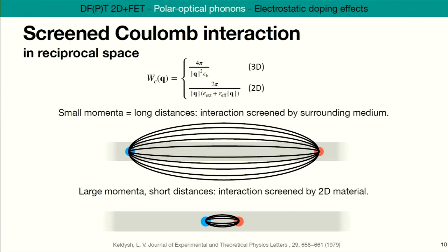So let's look at how it works. First, at small momenta. Small momenta correspond to long distances in real space. This corresponds to this term here being zero, or negligible at least, in front of the other one. In this situation, you have only this constant term here. If you imagine two charges far away from each other in a slab of 2D material, the electric field lines representing the interaction between them are going to go through outside the material. So this electric field is going to be screened by whatever is around the material, the environment. This is exactly what we see here. This constant has this X indication that says the screening comes from the exterior, I mean the environment.